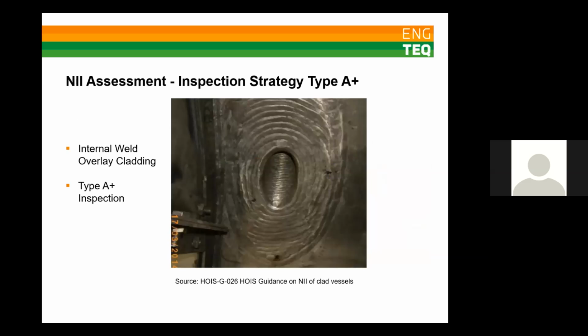Moving on to a type A plus inspection. This image is taken again from the HOIS guidance notes on the NII of clad vessels. You can see the outer areas are hot rolled clad. So these are nice smooth areas with a nice uniform surface. But at the area of the nozzle protrusion and inside the nozzle bore, these have been clad with weld overlay cladding. So this results in a much coarser surface with an uneven surface, where the unevenness is determined by the width of each weld bead. You also end up with a coarse grain structure, which can cause difficulty in inspection.